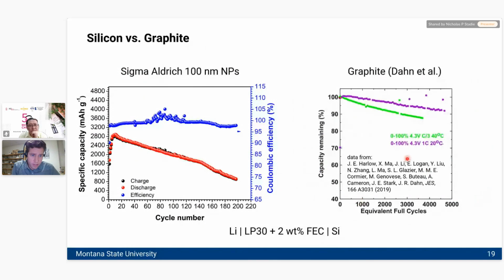To compare with graphite, this is basically the benchmark set of data that are currently collected on graphite. This cell is the famous Jeff Dahn 4 million-mile cell, and this cell has been cycling in the lab of a very famous battery chemist by the name of Jeff Dahn up in Halifax, Canada, for years, and it's got now some 5,000 cycles, still above 95% of its original capacity, which again for graphite is 372 milliamp hours per gram at best. And so while that's a low number, on the left plot, that's an extraordinarily stable cycling, and we can see that these data on the left will definitely intercept 372 here well before even 500 cycles are passed.